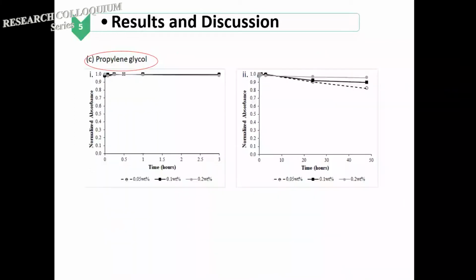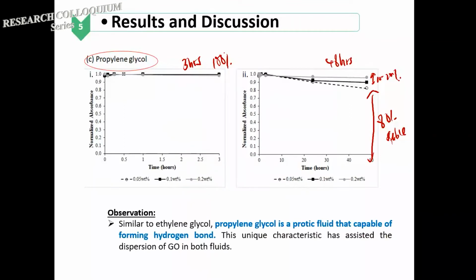Now, similarly, for the propylene glycol, up to 3 hours, there is almost no sedimentation. How can this be achieved? Even after 48 hours, you can see only about 10 to 20% undergoes sedimentation. More than 80% is still very stable. So that is something good also for our application. It's similar to the ethylene glycol. Propylene glycol is a protic fluid that is capable of forming hydrogen bonding. So this could be the reason why the graphene oxide is able to stay stable in this propylene glycol solution.